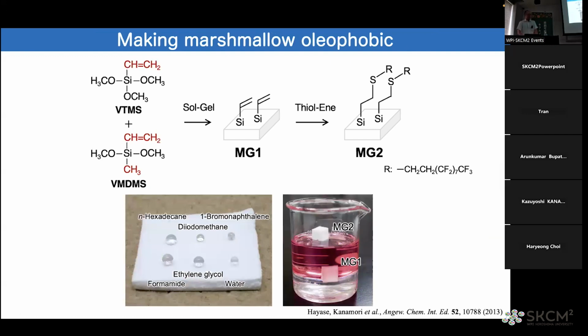Then next, we tried surface functionalization of this marshmallow gel because, for fun, we wanted to make the surface of marshmallow gel oleophobic. So we prepared marshmallow gel from these vinyl functionalized precursors. Then after the preparation of the gel, we did surface modification with a perfluoroalkyl thiol by the use of thiol-ene reaction. Then we can add the oleophobic molecules on the pore surface. So we found that not only water, but also ethylene glycol, formamide, different organic liquids, even hexadecane, which has a very low surface tension, this material can repel all the liquid.